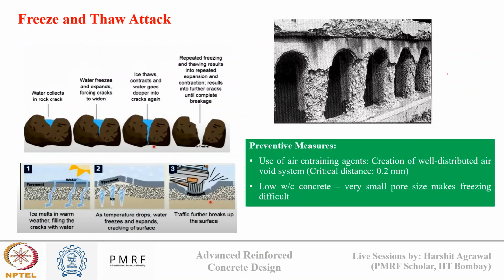So here you can see some examples of what is happening due to freeze and thaw attack, or we say frost action. In the first image you can see how this frost action is causing rock to crack. Initially water was collected. Now water freezes and expands, which causes cracks in this rock. As the ice melts, the water will penetrate to a deeper depth. Then again it freezes, it expands, and it causes the crack to propagate further inside. In this way water goes deeper and deeper inside this rock, and finally at one point it will crack the rock. So it is the freeze thaw effect that is causing the cracking.